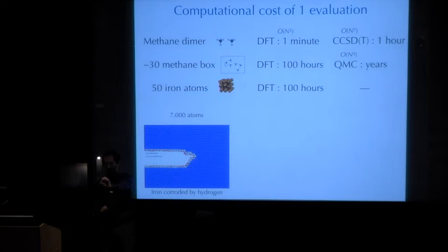Now, I think I know why you're asking this. There are some systems where this locality isn't there, or not so exact as I say. That's where Coulomb interactions and dispersion interactions are longer range. And that's where you and I have been discussing how to bring in the multi-scale nature of those parts of the interaction. I've been carefully avoiding them for the past 10 years, really focusing on systems where at least the energy instantaneously is local, but in order to, for example, do force fields for proteins, we will need much better control over the Coulomb interactions and the parameters of them, which is not local.